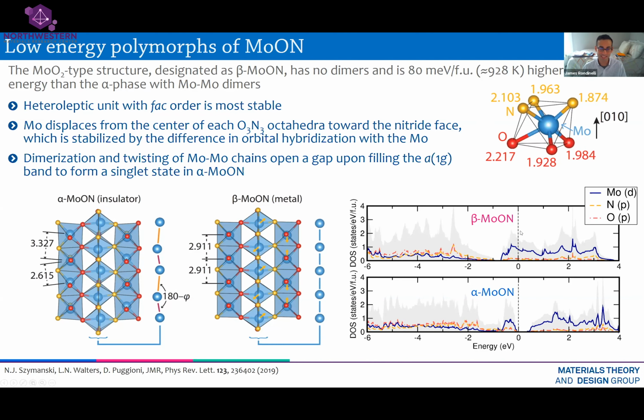And so in the metallic phase, the beta phase, here's the density of states again as a function of energy. The Fermi level is at 0, this dashed line. You can see that the Fermi level cuts through a band which is derived from the molybdenum d states.